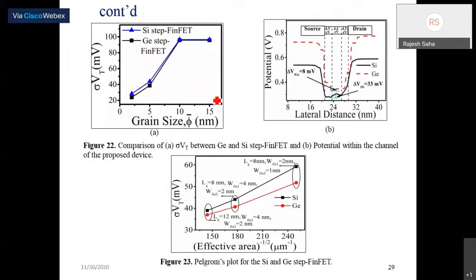We also used some other channel material. We have considered germanium as the channel material instead of silicon. We observed how it behaves with the various channel materials. In the germanium step device, as you can see, it shows less variation in the threshold voltage compared to silicon up to this range. But from here it got saturated.